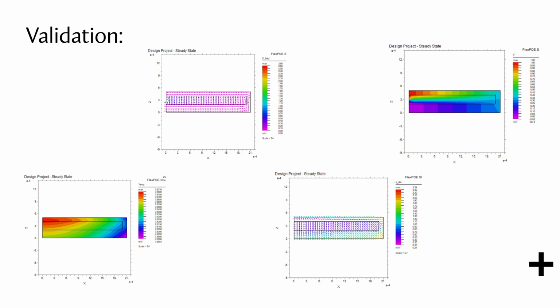First, the piezoelectric portion of the model has been validated, setting up the model to use the same conditions and material properties as those of DA4 and comparing displacements with the original code. Displacement produced by the piezoelectric and thermal expansion alone was in line with the DA4 code, validating the geometry of the model. The plotting functionality was used to validate the electric field and voltage plots. The electric field plots showed that the field was applied in the correct direction, with the most going through the piezoelectric as expected. The voltage plot also showed that the model was working correctly, with the voltage gradient becoming distorted as contacts moved away from the left where the dielectric was between the metal layers.